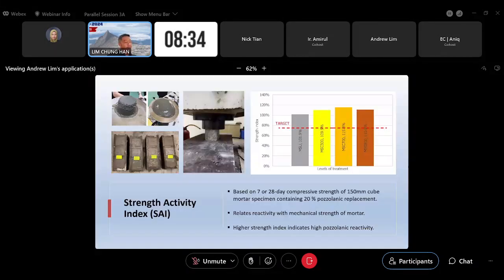The first method that I'm going to use is the strength activity index method. This method is basically based on strength. You're assuming pozzolanic reactivity is related to mechanical strength. So we cast mortar cubes. We cast a control set and a few sets containing the SBA, pozzolanic materials. The control sample would be set at 100% strength index, and then for all the test materials, you would assess the strength in relation to the control sample strength, 100%. If it's more than 100%, that means your specimen is stronger than the control sample. If it's less than 100%, that means it's not as strong as the control sample.